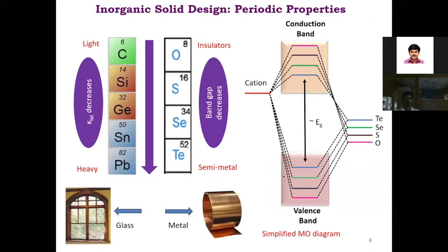In order to understand that part, we have to understand a little bit of the periodic table. So let's see in this chalcogenide series, which is oxygen, sulfur, selenium, and tellurium. If I fix the metal and go from metal oxide to metal sulfide to metal selenide to metal telluride, the band gap decreases enormously.